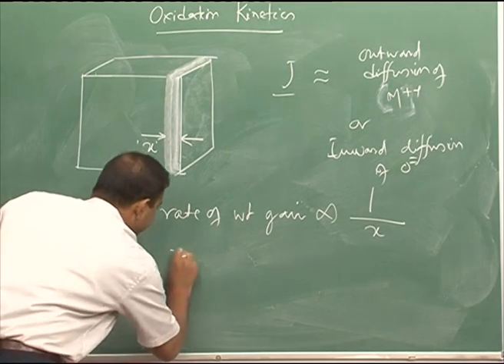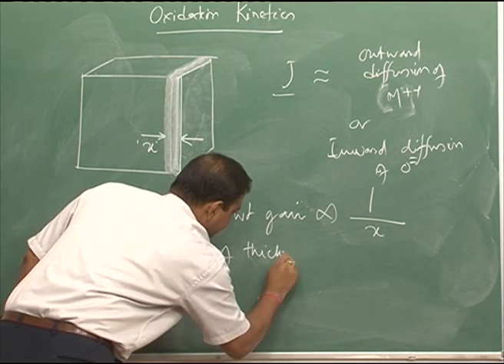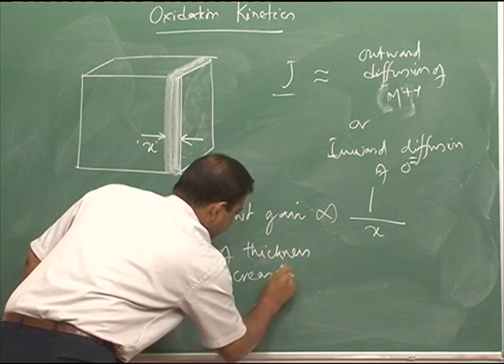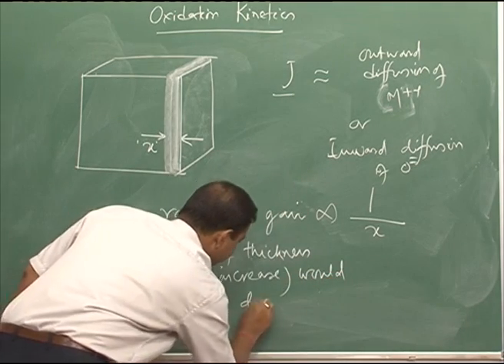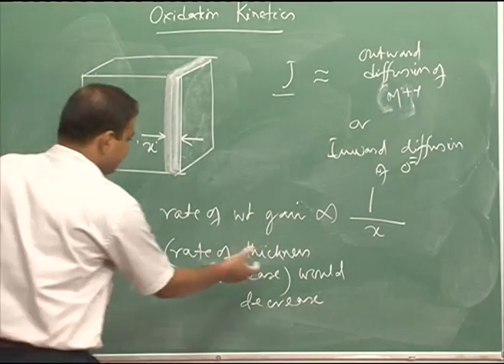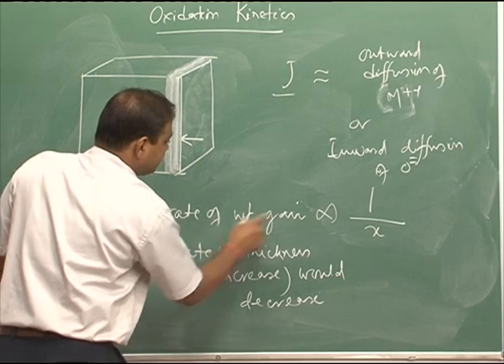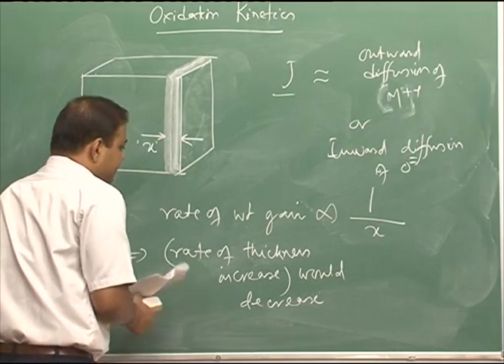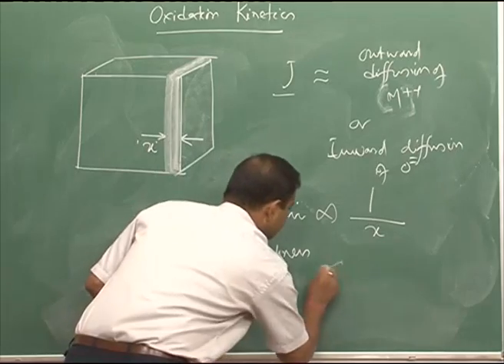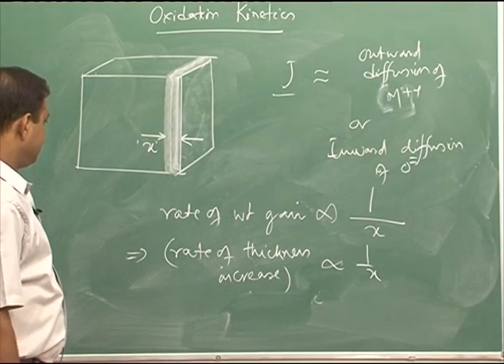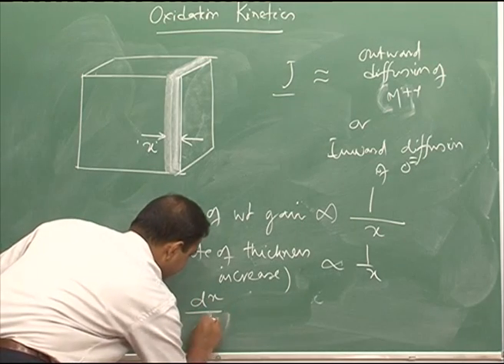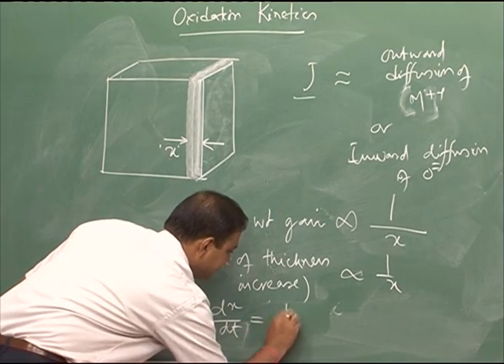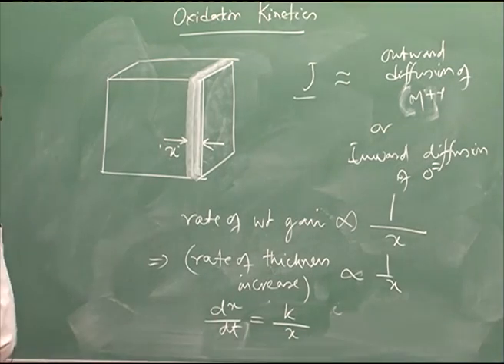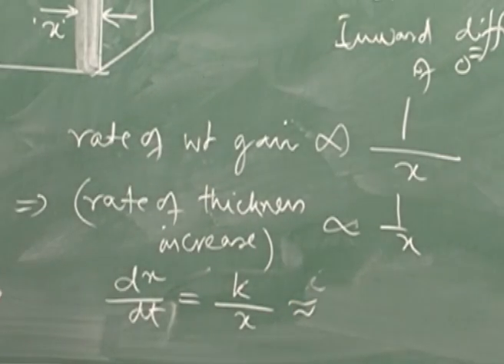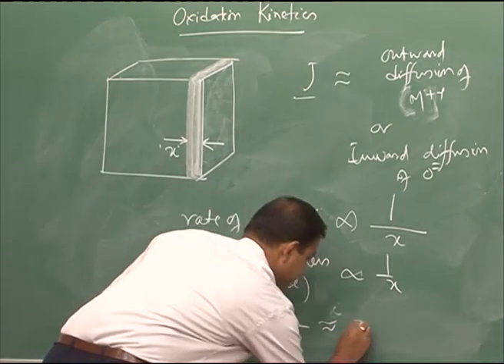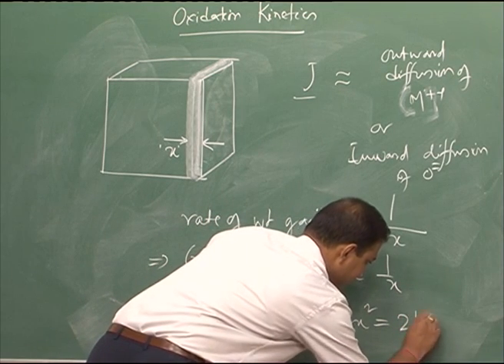So, it means that the rate of thickness increase would decrease. So, that means if we consider the rate of weight gain proportional to 1 by x, then the rate of thickness increase would also be proportional to 1 by x. Now, rate of thickness increase means dx dt would be equal to k, some constant, by x. And if we integrate this, then we would get x square equal to 2 k t plus c.